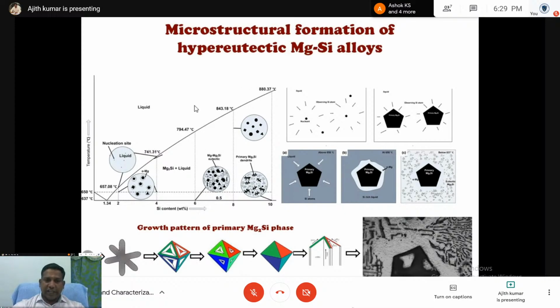In 6% silicon addition, we can assume the melt temperature is about 800 degrees or 850 degrees. After melting, when it starts solidifying at 794.47 degrees, the first phase is Mg2Si. That means primary Mg2Si will start. Then step by step it will grow like a polygonal type of structure. Then surrounding that, it is taking silicon from the outer region. So the surrounded region is silicon free region.